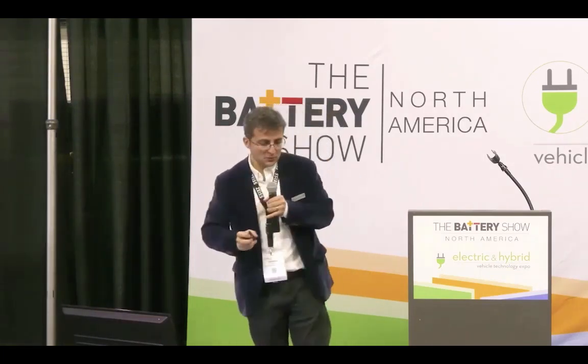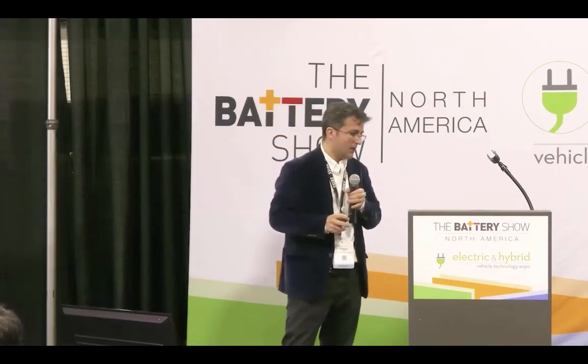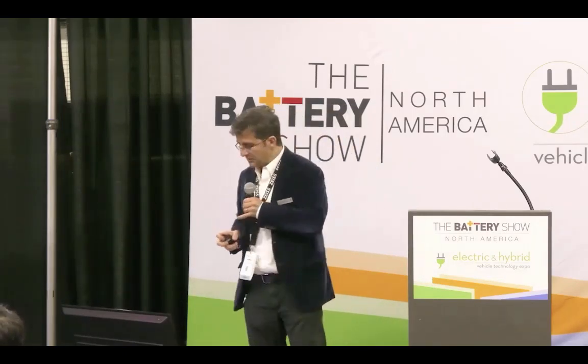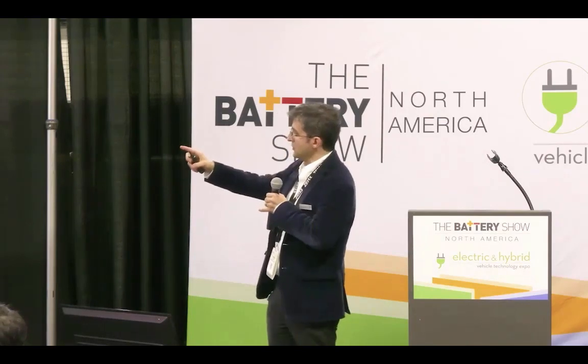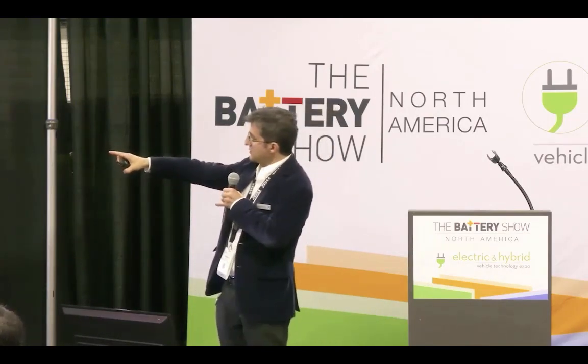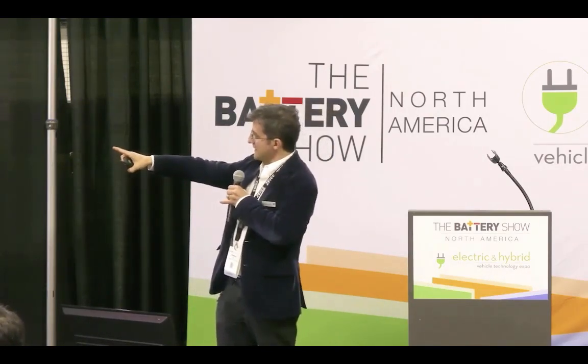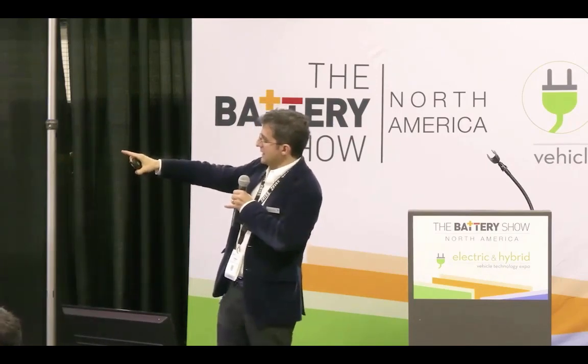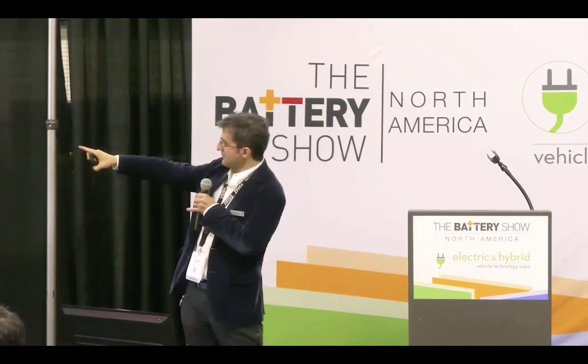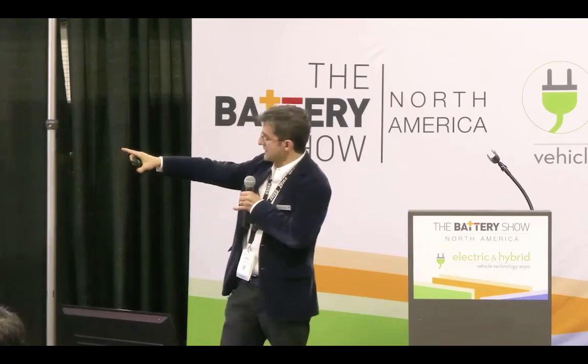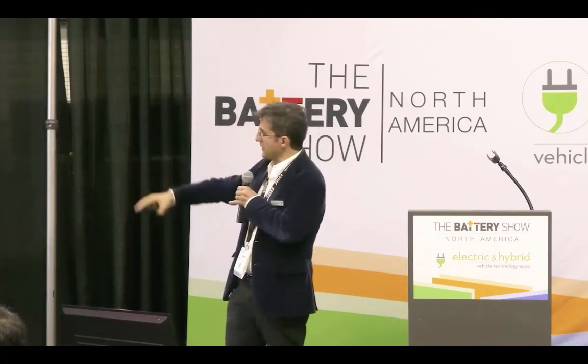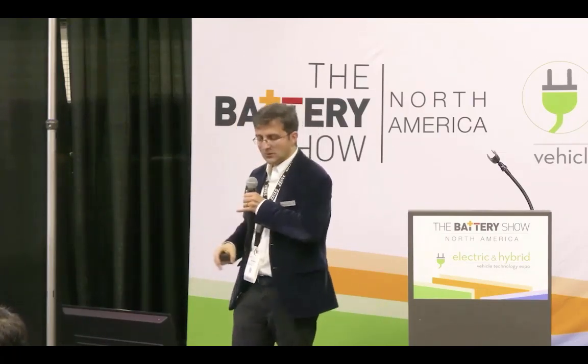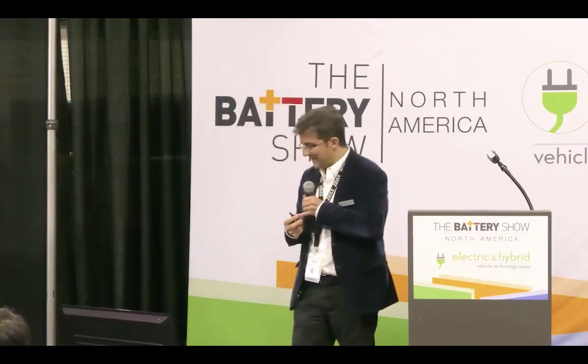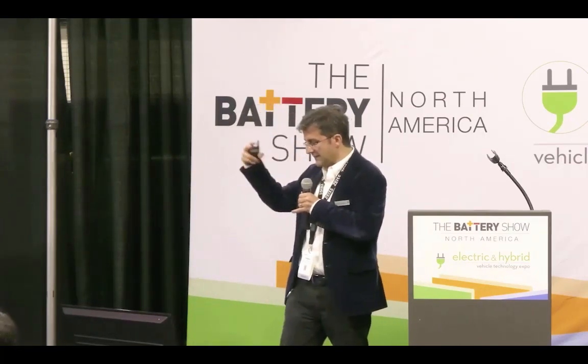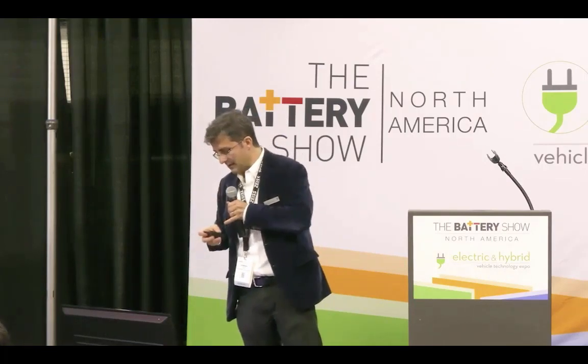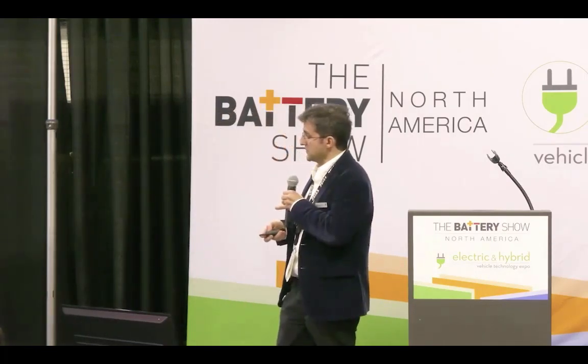When you want a much higher resolution, you could go all the way down to nanometer resolution, such that you can see details at the particle levels. And you can see some of the particles here have been cracked, and they are split in two or more pieces. This is also quite important to determine what happened after several cycles of charging and discharging on the type of material that you're using in your batteries.